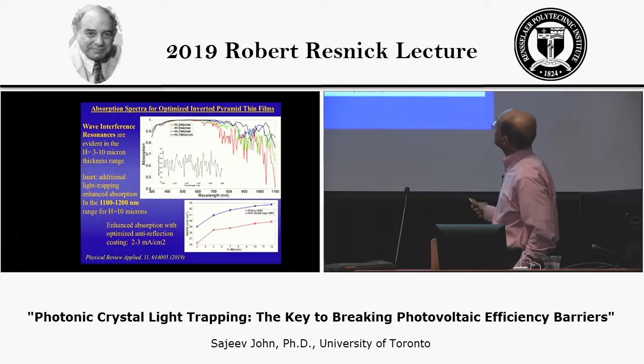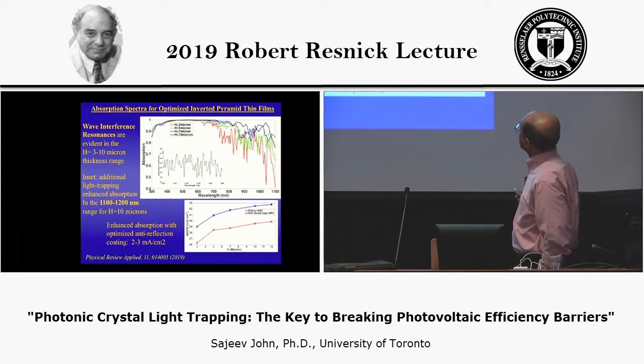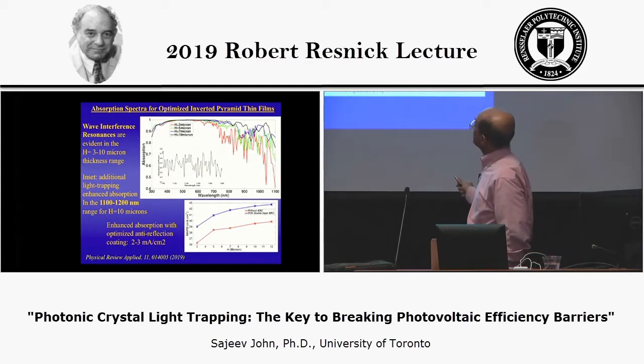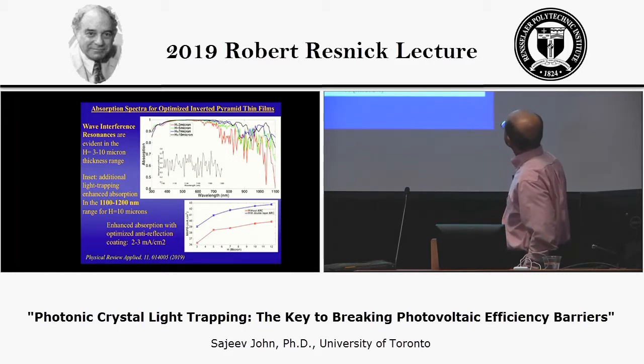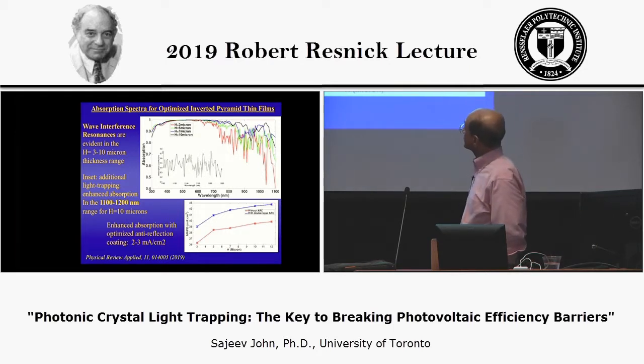So here's some more detail of the wave interference-based absorption spectrum for different thicknesses, ranging from the red curve, which is a 3 micron thickness structure, up to the black curve, which is 10 microns thick. So each of these peaks represents some optical resonance that's being created by wave interference effects.